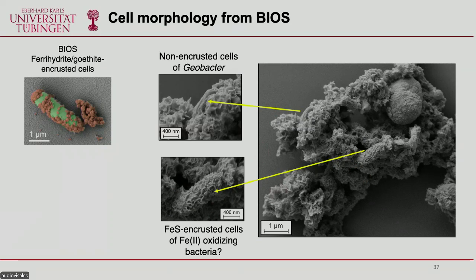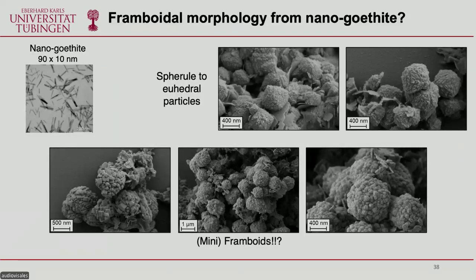And in one setup in particular, the one with nanogoethite, we see again pyrite that has a lot of these framboidal to maybe euhedral particles. But look at the pictures in the bottom row here. We see crystals that seem to aggregate together into more or less a spherical shape. And this roughly fits the definition of framboids. We're not really sure if these are real framboids. So at the moment, we call this either framboid-like or just mini framboids. And so that was really exciting when we were able to see this.